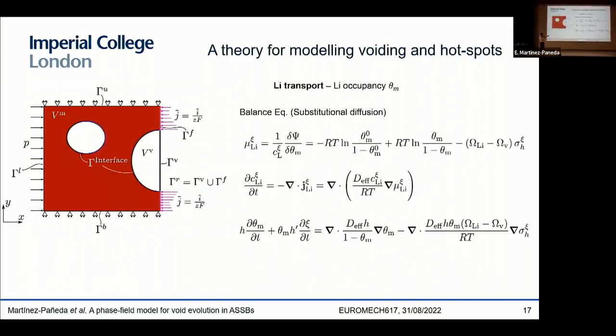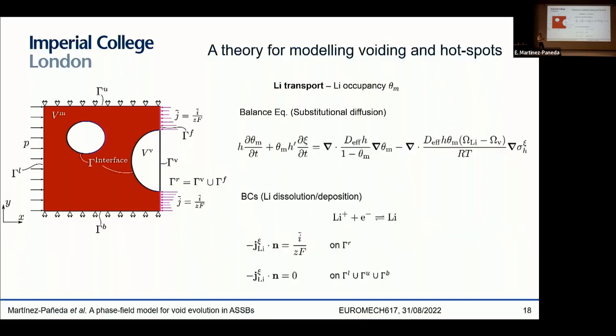And here you can see the example for lithium transport. I think two things that I want to emphasize here is that the model naturally captures the enhanced diffusion that you should see in the surfaces. And this is done through this term here, because the gradient of the hydrostatic stress will be strong along the void surface. And something that is a bit more interesting is that through the boundary conditions of this transport problem, you can capture those interface reactions, that lithium deposition and dissolution that you get when you do plating and stripping. And this is captured through this flux boundary condition that is dependent on this local current density that you have in there. And so it will change sign whenever you have plating and stripping.